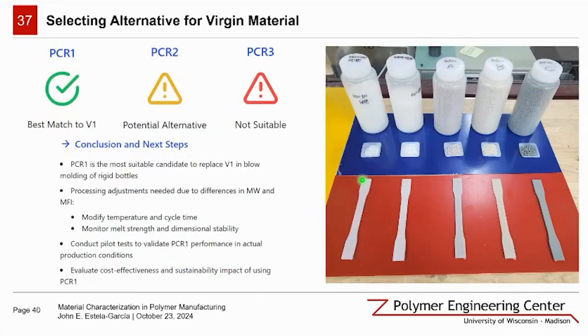So based on this comprehensive analysis, we've identified PCR1 as the most suitable candidate to replace virgin 1 in our blow molding of rigid bottles. PCR1 demonstrated thermal properties and crystallization behavior that are remarkably similar to virgin 1, along with comparable mechanical performance. However, it is important to note that PCR1 did have a lower molecular weight than virgin 1. And this is typical, again, for recycled materials.